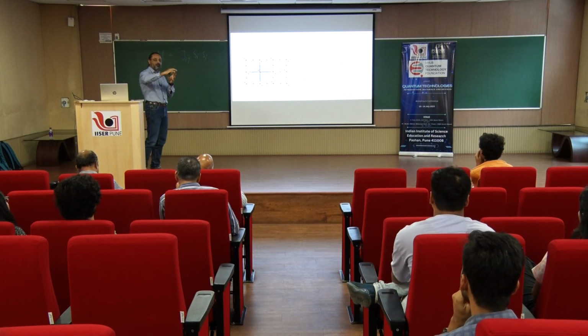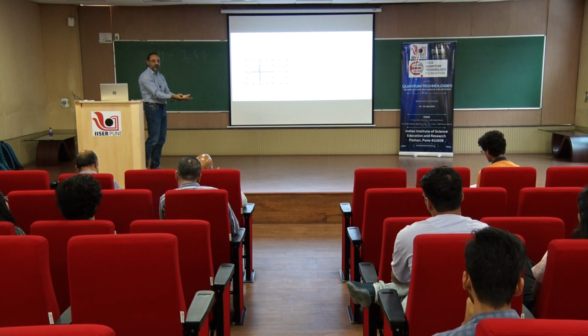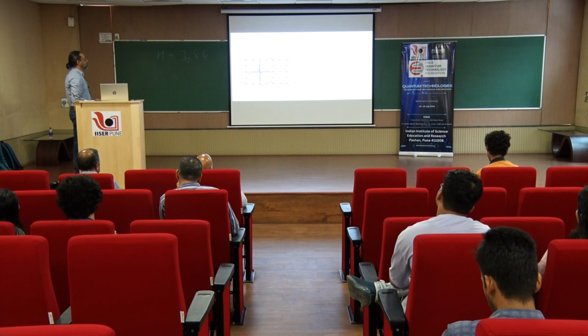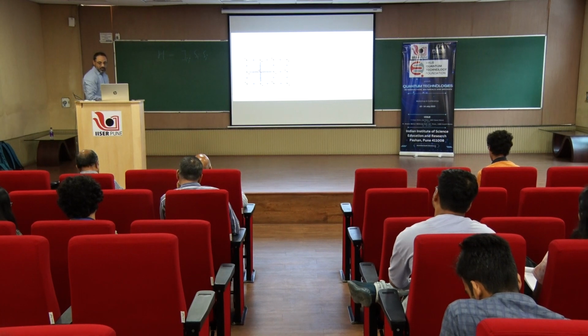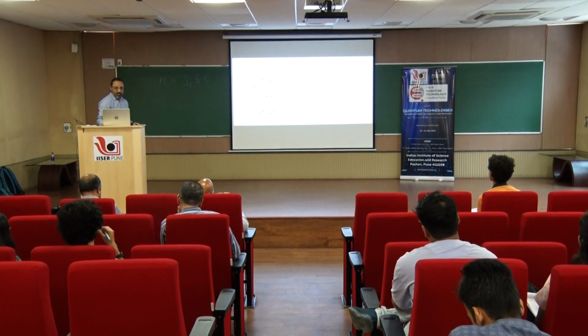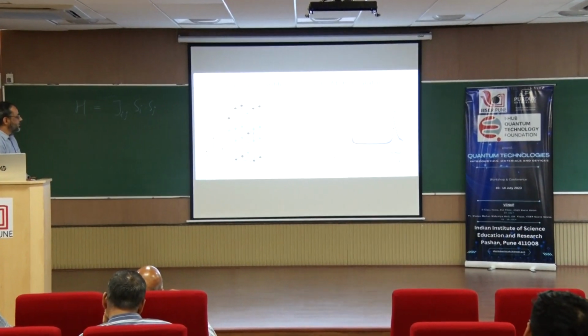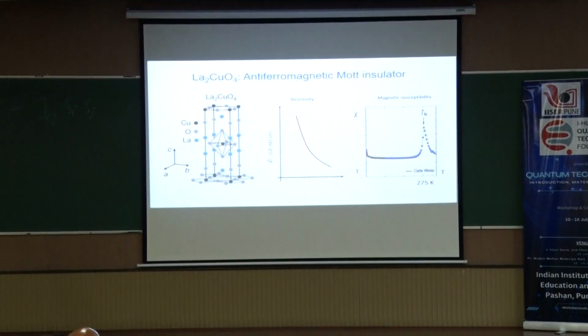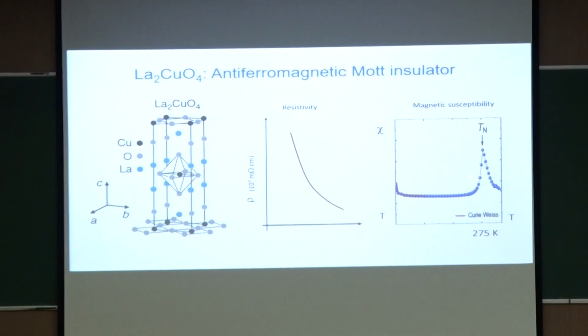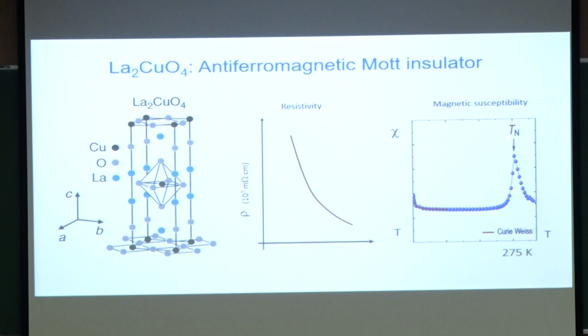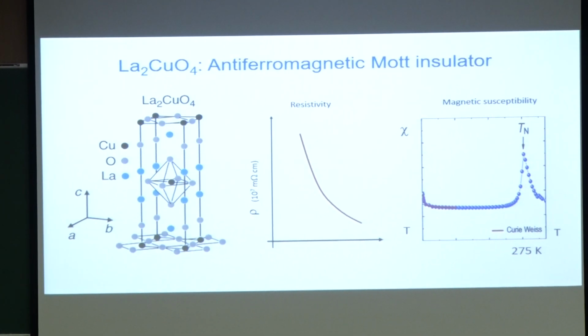So basically what's happening is that this localized hopping back and forth is bringing the energy down. All right, this is called virtual hopping, and this mechanism is known as the superexchange mechanism, and this gives rise to an antiferromagnetic ground state. So what we have learned then is that La2CuO4 is not only an insulator, but it also orders magnetically below a certain temperature. There is a spontaneous ordering, and this temperature is known as the Néel temperature. All right, so this is an antiferromagnetic Mott insulator.